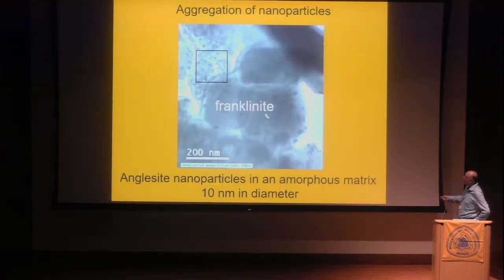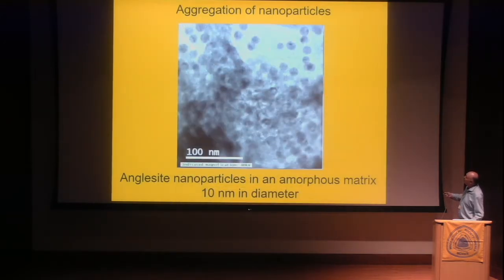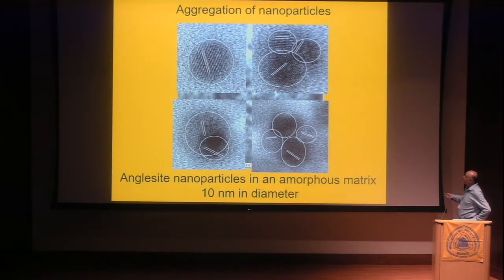So the first thing we recognized is the aggregation of nanoparticles. So we have here a crystal of franklinite, a zinc spinel, and we see here those nanoparticles, and we zoom in. We can actually see the anglesite nanoparticles aggregating and agglomerating. And when you zoom in, you can really nicely see how those aggregation processes follow. So we have here one nanoparticle of anglesite, and it merges with another one. Then you have 2, 3, and then 4 nanoparticles. So you can really observe the agglomeration of nanoparticles in those confined pore spaces.